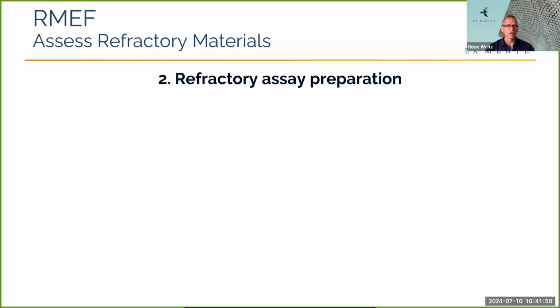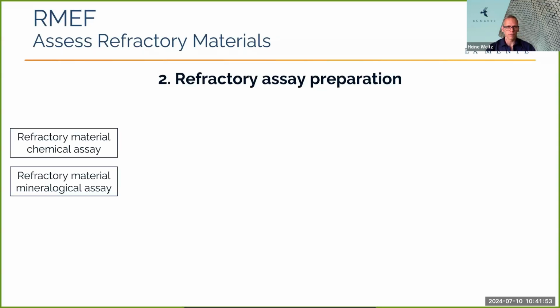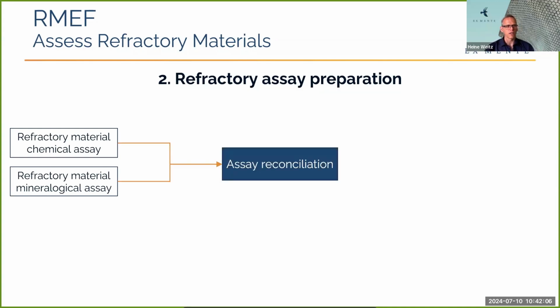Okay, then we need to go into refractory assay preparation. So we start off with a refractory material chemical assay and also a mineralogical assay. Both of these are important. Typically, you only get a chemical assay from the refractory suppliers, but it's easy enough to do a mineralogical assay. And based on that, you can do an assay reconciliation to make sure that your chemical and your mineralogical assay are actually in agreement. And that helps you to prepare the reconciled refractory assay, which you will use in the next step.